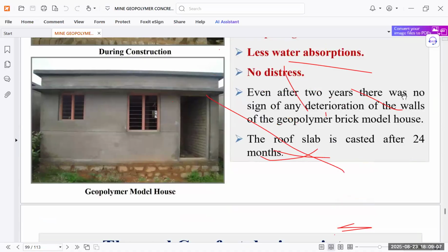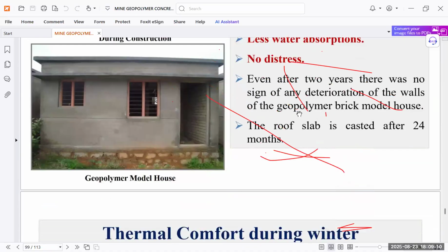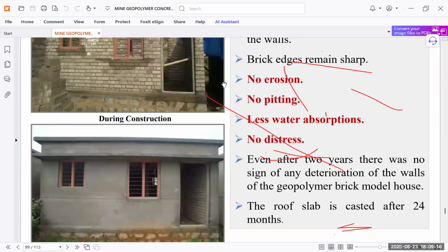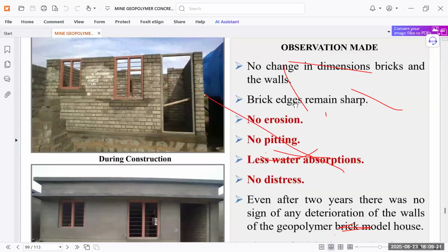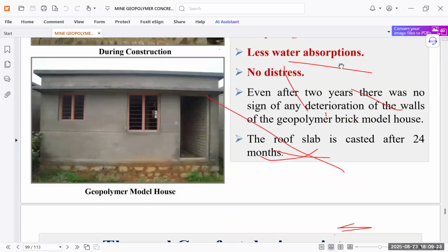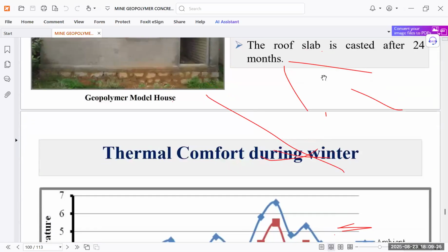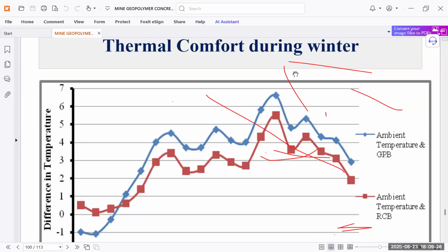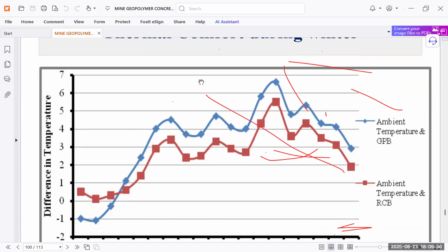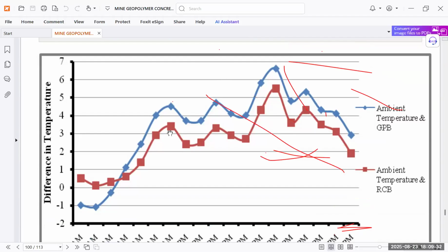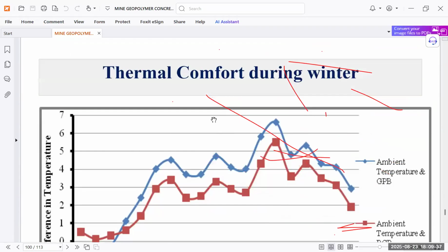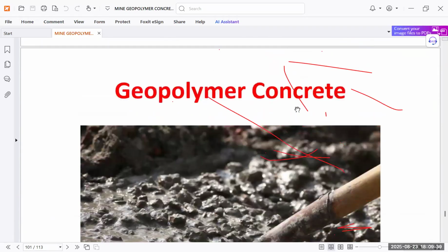Even after 2 years, there was no sign of any deterioration of the walls of the geopolymer brick model house. The roof slab was casted after 24 months. So you can see this model is showing no erosion, no pitting, less water absorption, no distress seen, and no change in dimension of bricks and the walls. And the roof slab is also casted after 24 months. Then thermal comfort during the winter is there. You can see the ambient temperature, and this is the temperature in the GPBS. So thermal comfort is also there using this GPBS.